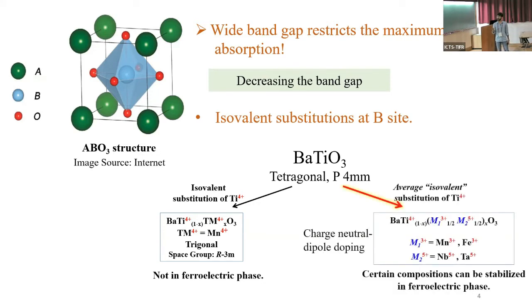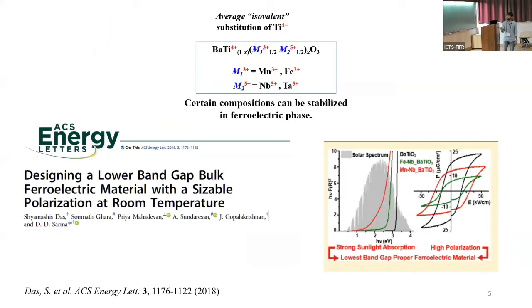To overcome that, we devised an average isovalent substitution strategy, or I should say a co-doping strategy, to use a metal atom of valency less than 4+, say M1 3+, and another metal atom of valency 5+, which is one more than 4+. Candidates for M1 3+ can be chosen as manganese 3+ and iron 3+, and M2 5+ candidates can be chosen as niobium 5+, not shown here, and tantalum 5+. The benefit of such a strategy is that certain compositions can be stabilized in the ferroelectric phase at a certain doping level. So using this strategy, Shyamashis Das et al.